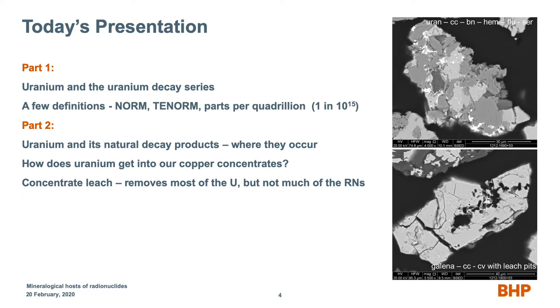Sorry, that's a little bit bright in the background. This is a 30 micron size particle. It's a particle that contains chalcocite, bornite, some hematite, and the brighter white things, in all the images we see brighter white, are just uranium-bearing particles. So nice to see a beautiful composite particle. That's in concentrate. That's in our con. They all don't look like that, but they're there.